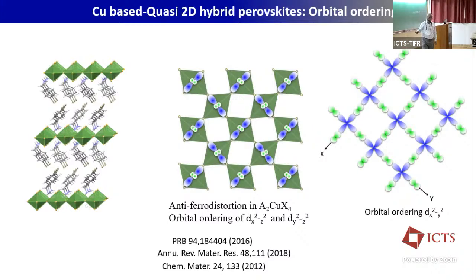But in this kind of system, the elongation, the distortion, happens in the plane, so that you get a kind of orbital ordering. You can see one long and short bonds, they lie in the plane. Because of that, you have an orbital ordering like dx²-z² and dy²-z². So unlike the parent compounds of high-Tc cuprates, which are mostly antiferromagnets, because of the orbital ordering, in this kind of copper-based material you find ferromagnetism.